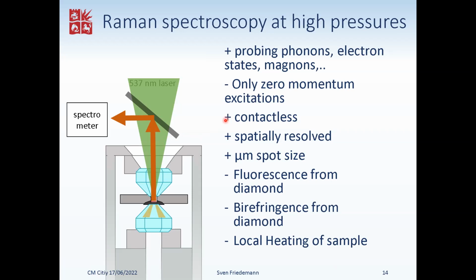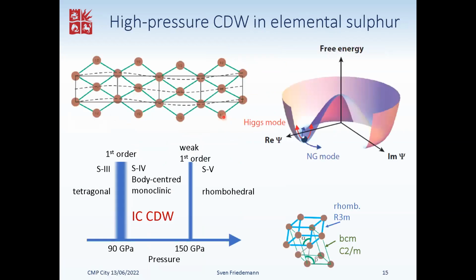In particular, we've been able to probe the amplitude mode of the charge density wave in elemental sulfur. So sulfur, you've got it in mind that at ambient pressures, of course, it's a yellow insulating material, but at high pressures, at about 100 GPa, it turns into metal, nice shiny metal. And it in fact hosts an incommensurate charge density wave between about 90 and 150 GPa.